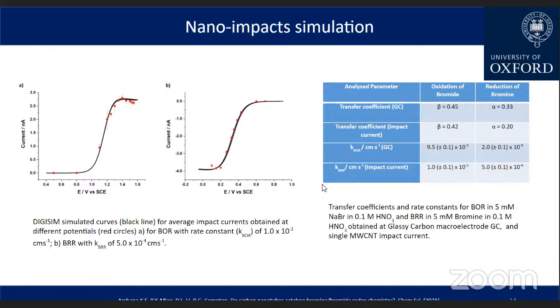In the bromine-bromide reaction, the electrode is coated with the carbon nanotube or any catalyst for that matter. Carbon nanotubes or any carbon materials are hugely stable and quite inert to these reactions. They just act as a surface where the reaction is happening, and they usually stay there for a really long time. It doesn't corrode or come off with the electrolyte. If you want to change or recycle it, you just have to remove it and recoat it with another layer of carbon nanotubes. That's how it practically works in large-scale batteries.